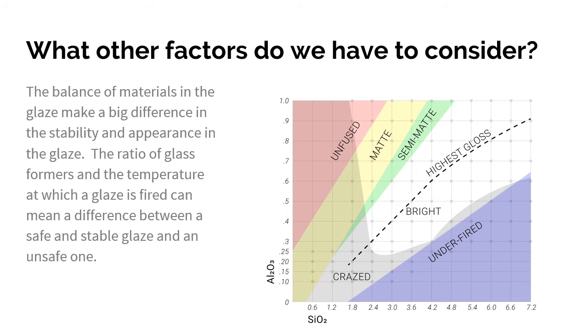And a lot of times there's a lot of online resources where artists share recipes for glazes. And they'll say, hey, look, I made a really cool matte glaze. It's super stable. It's really predictable. And if you accidentally overfire it, it comes out of the kiln and it's super shiny. And if that's the case, that really means that the balance of glass stabilizer and glass former was not correct, and you haven't, in fact, made a stable glaze. So a matte glaze that is reliable and food safe can be difficult to find because of that chemistry involved.